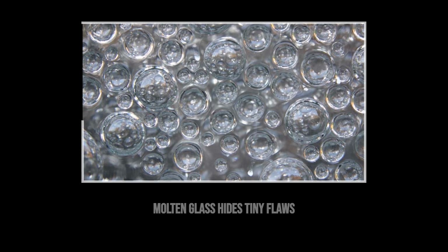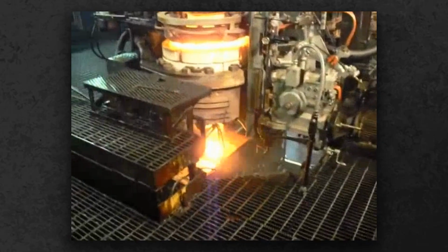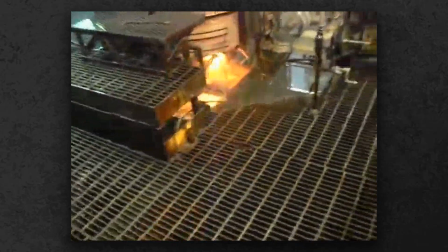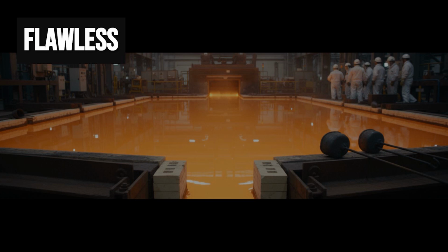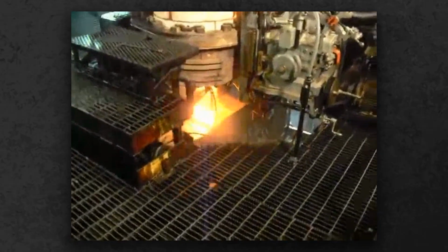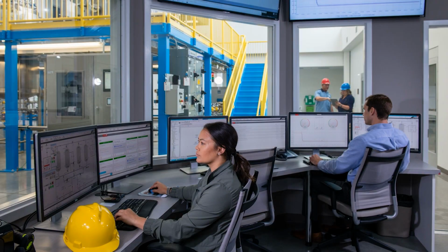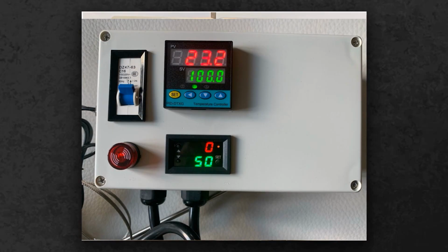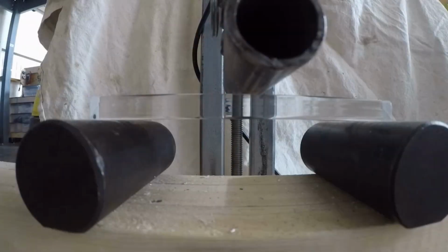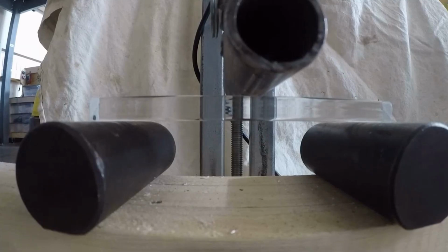Tiny bubbles and streaks can ruin the strength and clarity of finished glass, so technicians add fining agents like sodium sulfate directly into the melt. These chemicals trigger reactions that help trapped gases rise and burst at the surface, leaving the glass as flawless as possible. The entire mass is stirred and sampled, every movement calculated to guarantee uniformity. Even at this stage, the temperature is carefully managed. If it cools too quickly or stays too hot, the glass can become brittle or too viscous for shaping.